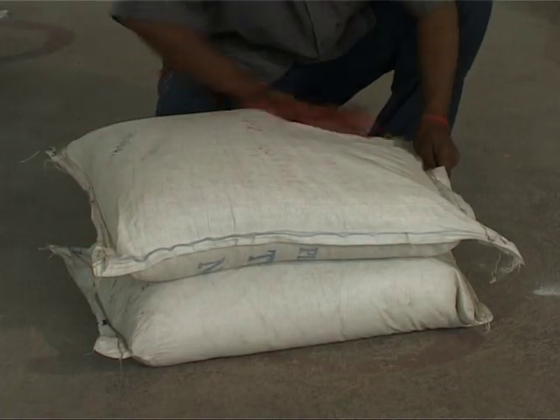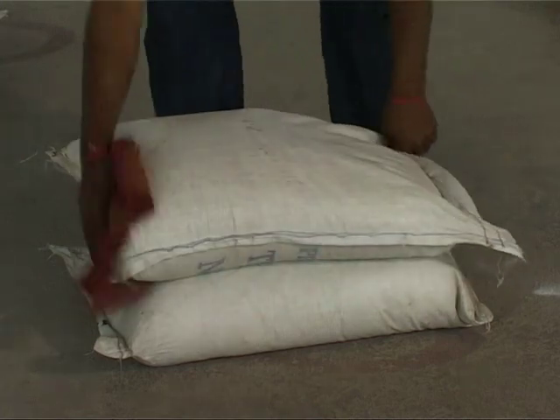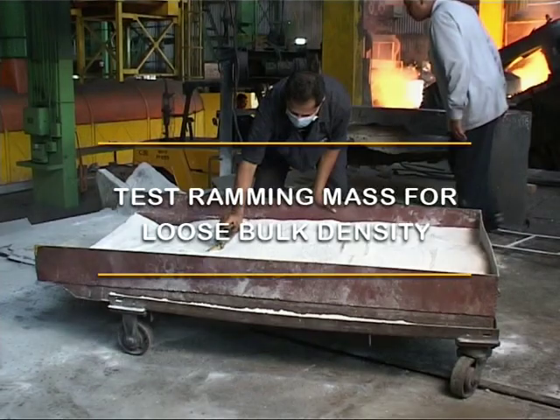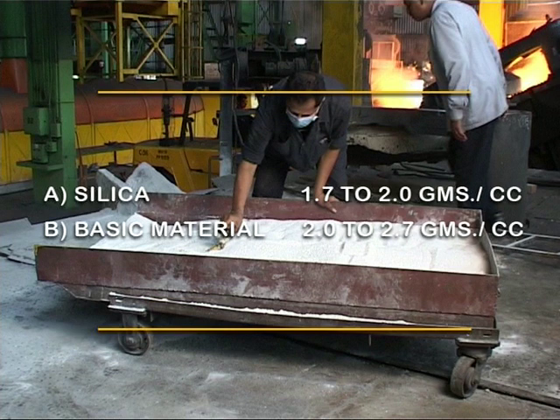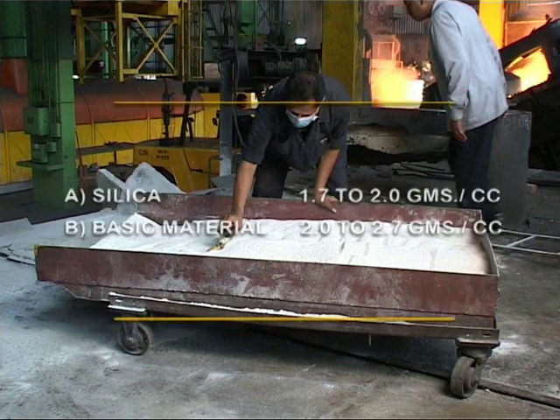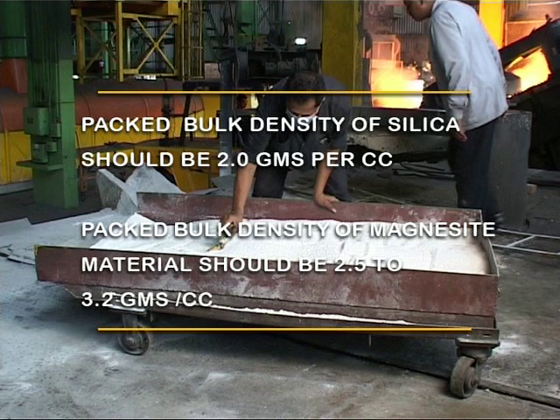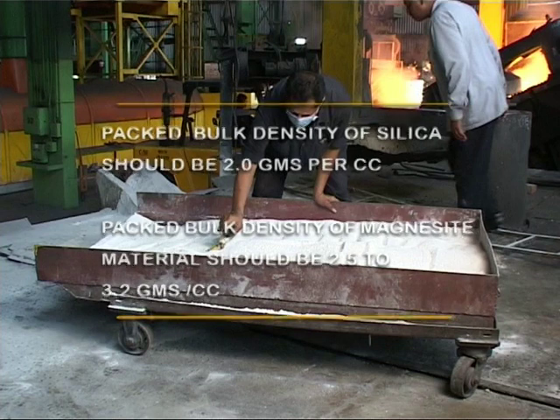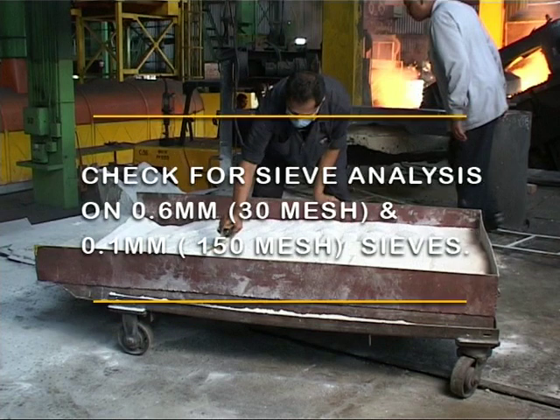Do not use ramming mass bags showing water stains or moisture content above 2%. Test the ramming mass for loose bulk density. Silica 1.7 grams per cc. This may vary as per the source. Basic material 2.0 to 2.7 grams per cc. Packed bulk density of silica should be 2.0 grams per cc. Packed bulk density of magnesite material should be 2.5 to 3.2 grams per cc. Check for sieve analysis on 0.6 mm 30 mesh and 0.1 mm 150 mesh sieves.